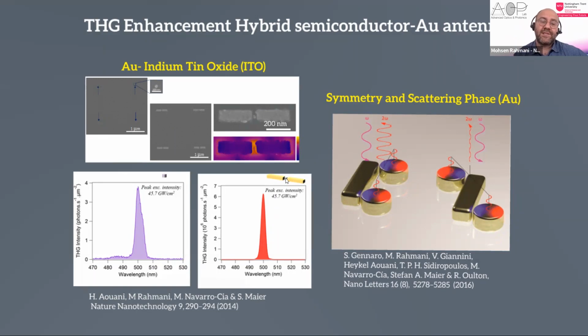And even taking advantage of the hotspot by putting some extra material in those hotspots. As you see here in this nice study, we had the dimer, and obviously we had this hotspot in the gap of the dimer, and we put one small nanoparticle of ITO over there, and we managed to significantly enhance the nonlinear signal in those years. But at the end of the day, the intensity of the plasmonic nanostructure didn't reach the level that can be used for application, and I will tell the reason in a minute.